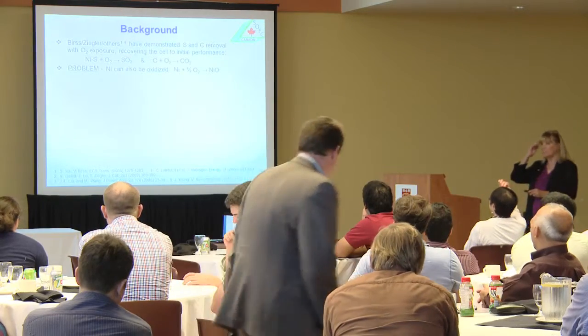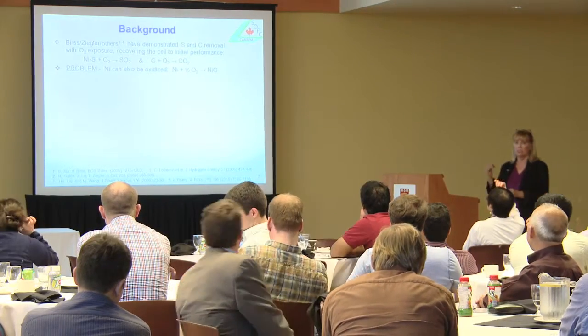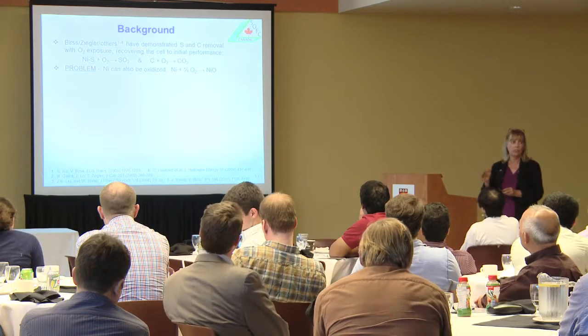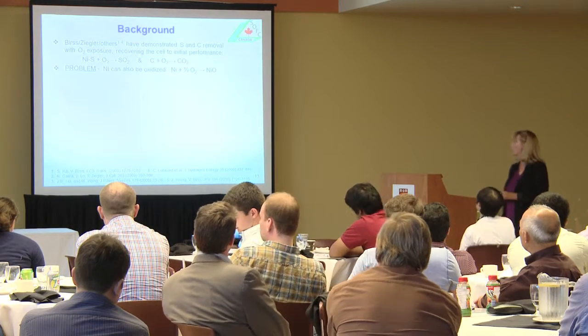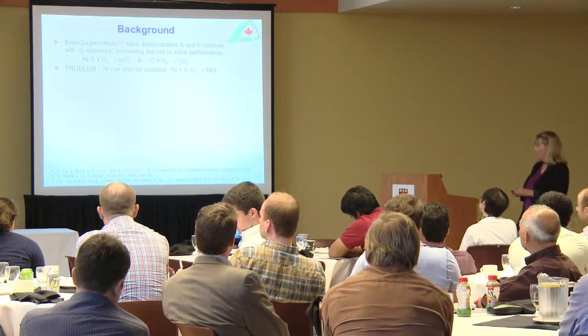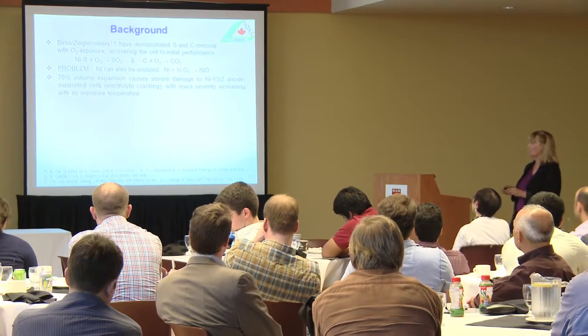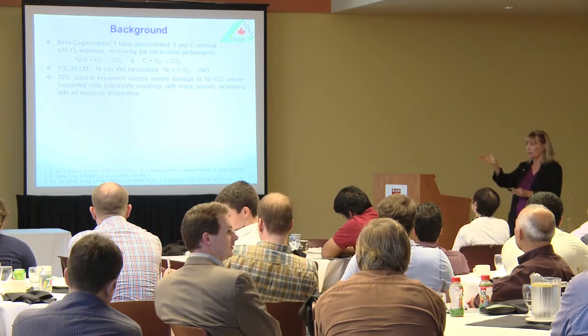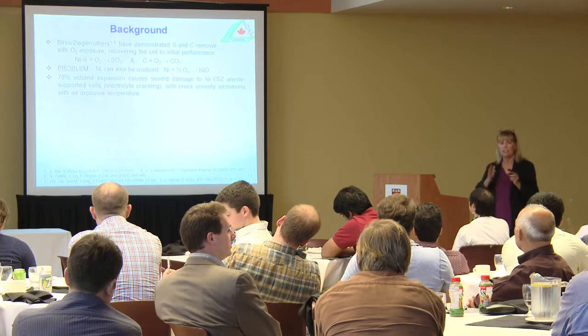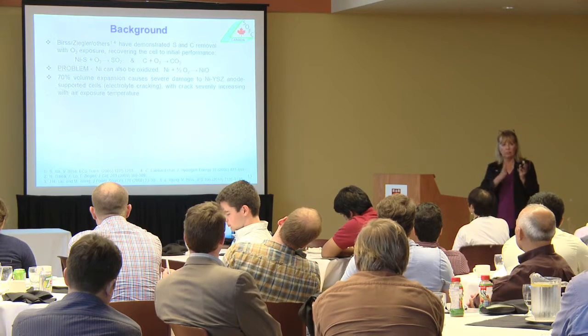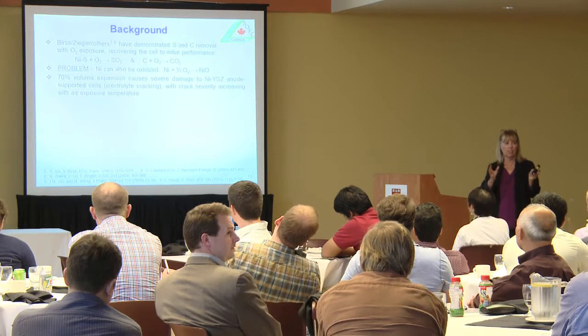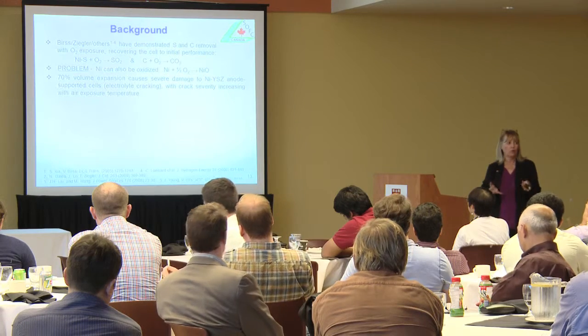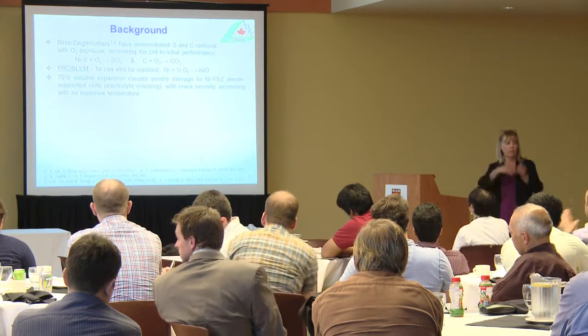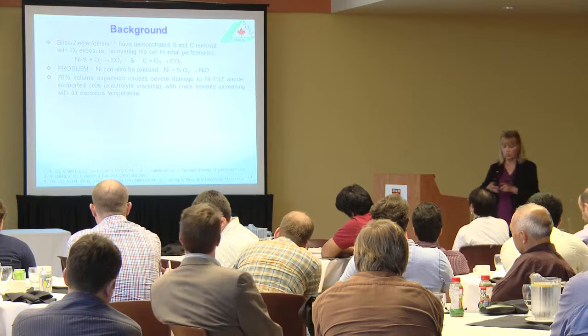So we've seen this before. We know that we can regenerate sulfur poisoned nickel anodes with a little bit of oxygen. But the problem is that you can also make nickel oxide. And thankfully, Partho talked about it this morning, that the expansion of nickel to nickel oxide is such that when it occurs in the wrong way, it can just crack everything, cause stresses, and fracture the electrolyte.